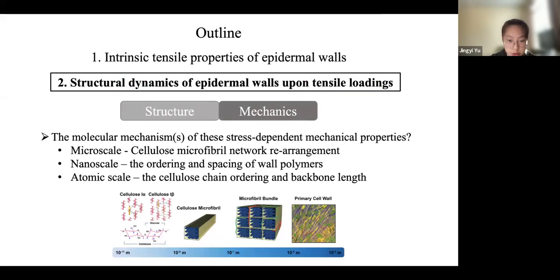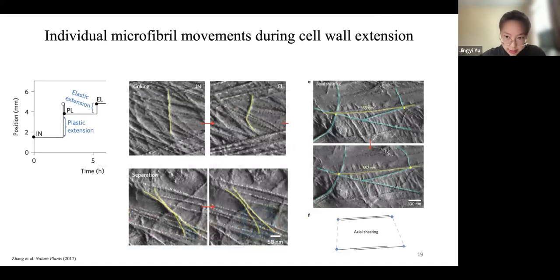To approach this question, we're trying to characterize the wall structure from different scales, starting from the microscale, where we can see potential network rearrangement, and the nanoscale in terms of the ordering and spacing of wall polymers, and finally the atomistic scale, to see whether the tensile mechanics result in any changes within the crystalline cellulose microfibril in terms of its length or packing.